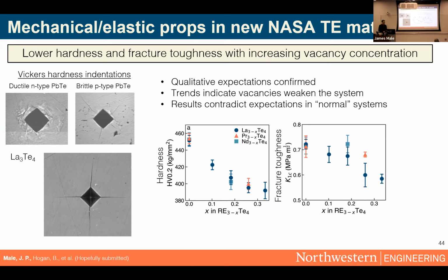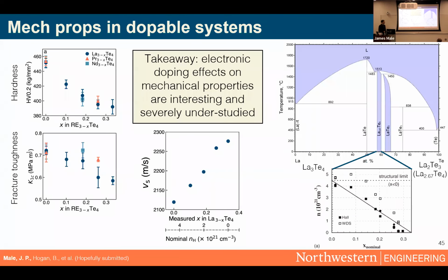Now, these sort of results that are going opposite the direction of sound velocity aren't necessarily what you would expect in a single metal or ceramic in typical mechanical properties literature. But a major difference here is we're essentially changing a material from a metal to a semiconductor as we add vacancies. There's really no other system that I've ever found explored where you can explore how mechanical properties change as such an aggressive change of doping occurs. So I believe these sorts of widely dopable thermoelectric materials are quite interesting for studying mechanical properties. And hopefully this study brings up some interesting points.